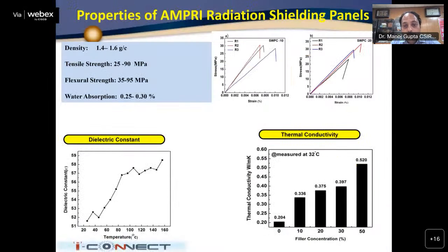Then another parameter: if we are using another metal oxide which has very high thermal conductivity, then scattering is another problem. When X-rays interact with any metal, different kinds of scattering occur. So our material must have low thermal conductivity. You can see that the thermal conductivity of the board is just in the range of 0.55 watt per meter Kelvin, very low. It means it has thermal insulating properties.